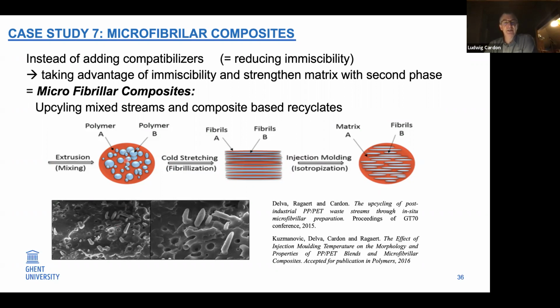So, in this case, you see material A and B. B is the inside material, for instance PET, let's say 20% PET. The red one, material A, is a polypropylene. When you have a 20-80 average mixture of that in waste, what we do is first a thorough blending, and after the blending the so-called cold stretching. By cold stretching, we create fibrillization. So we will have small fibrils of the PET material instead of spherical particles, surrounded by polypropylene material.